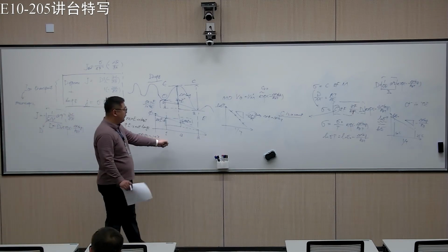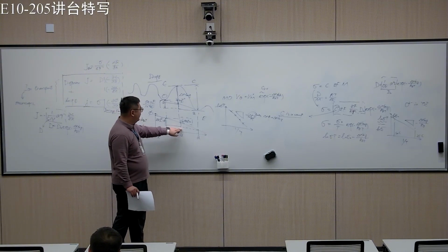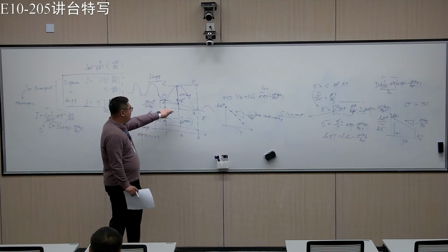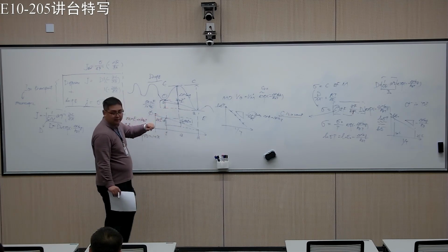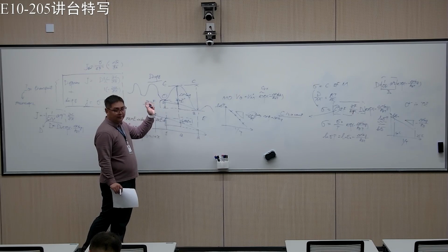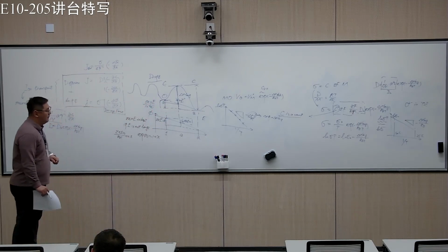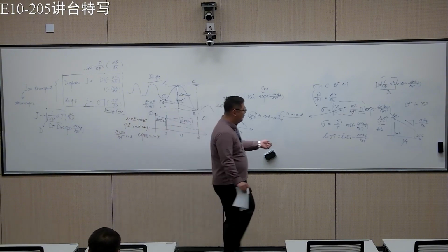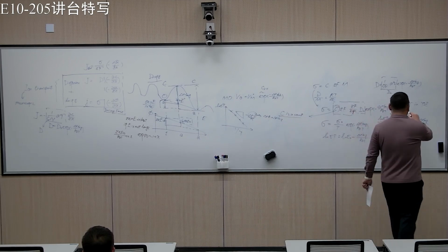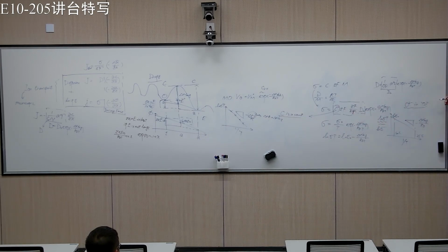We also talk about drift. We know that in drift, the electric field doesn't directly change the diffusion. It basically creates a change in the energy landscape. It's basically keeping the balance. Then the ions start to move. And finally, we talk about the conductivity as a function of temperature. One important thing is that you can really measure the conductivity as a function of temperature. If you get a plot like this, then you can get the migration barrier. So that's one important application.